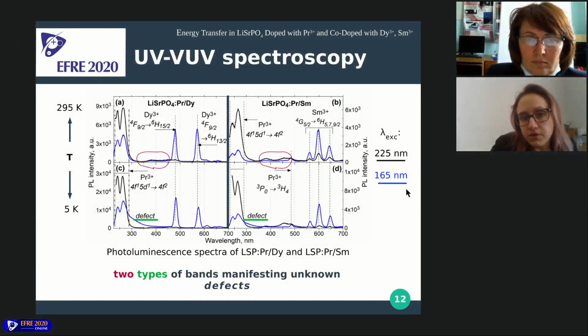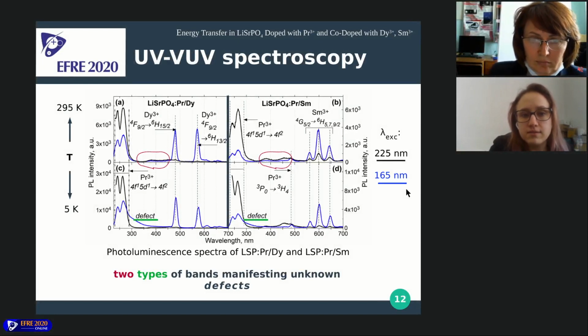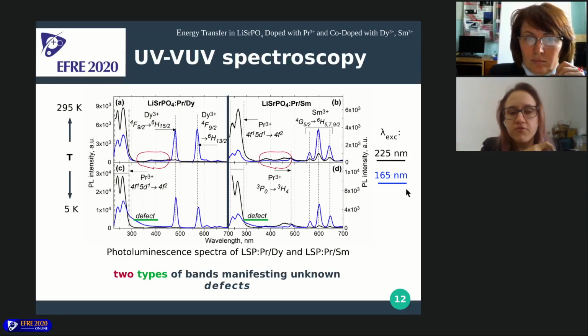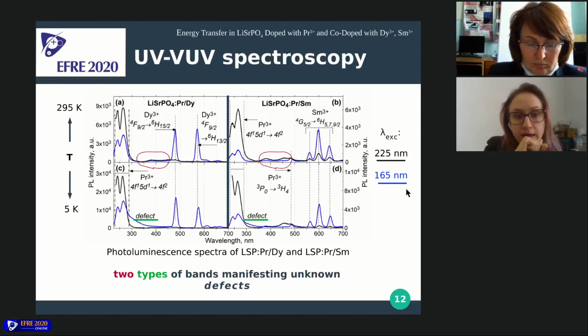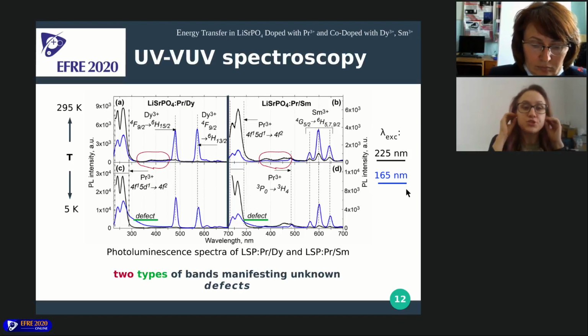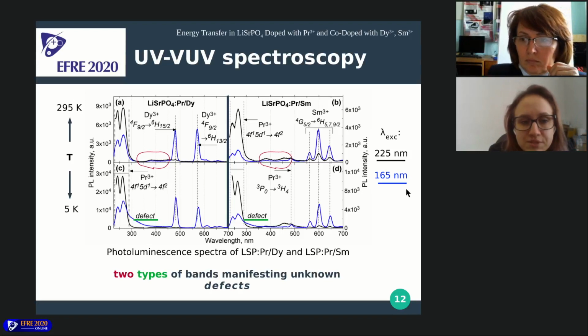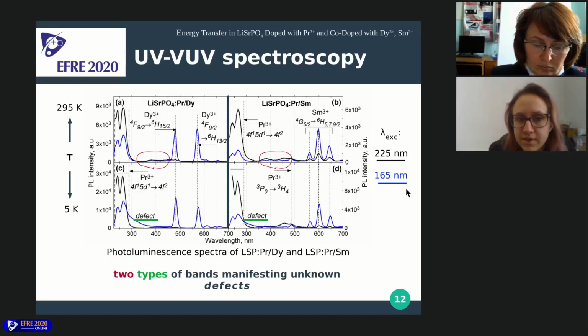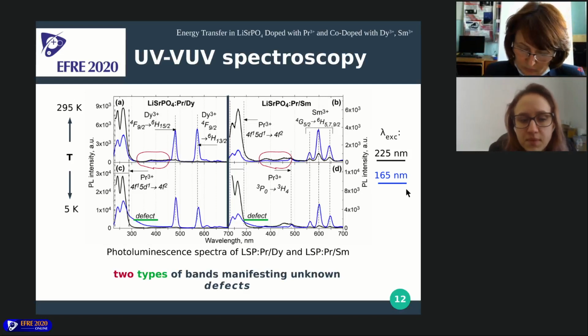To understand all the energy processes in this material, we had to use direct excitation. And here we use two types of excitation. The first one is 165 nanometers, which is very close to the energy of host absorption. And under this excitation, we can see praseodymium-3+ emission as well as the emission of codopants. Nothing interesting and nothing special about it, all as we have expected and we have seen in the cathodoluminescence spectra.